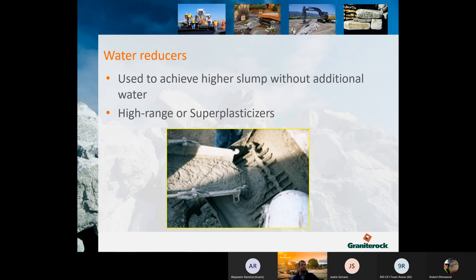Moving on to water reducers, there are different ranges like we saw in the types from ASTM 494. There's low range, mid range, and high range. These are used to achieve higher slumps without adding additional water. Adding water to concrete really creates a whole chain of effects that's negative for concrete: decreases strength, increases voids, and leads to other bad things. And use of high range or super plasticizers are also a component. Most of that is for large high-rise buildings getting through tight congested areas of rebar.